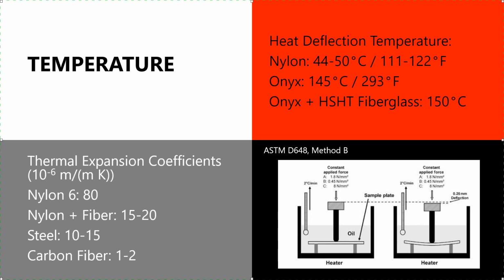It's substantially more stable at high temperatures, up at 145 degrees C or 293 F. And if you do the ONYX with the high strength, high temp fiberglass, or even the ONYX flame resistant with the high strength, high temp fiberglass, you're up in the 150 C range, and you're getting some really, really strong, durable parts, even at some really high temperatures. So that's where that operating range sits.